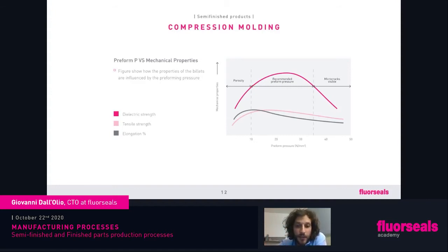As soon as we mold the same material at a higher pressure, say 20 megapascal, we can see that the elongation has dropped a bit compared to when we molded at 10, but the tensile strength becomes higher, and the dielectric strength is almost the best dielectric strength that we can get from that PTFE material. Going up to 35, we see that the mechanical properties, tensile strength and elongation, dropped a bit compared to 20, but again, the dielectric strength has been reduced. So this shows us how changing just one manufacturing parameter, the preform pressure, allows us to have different material properties.